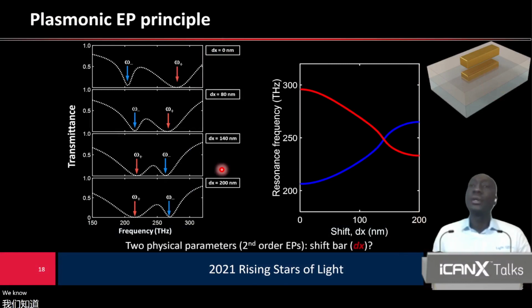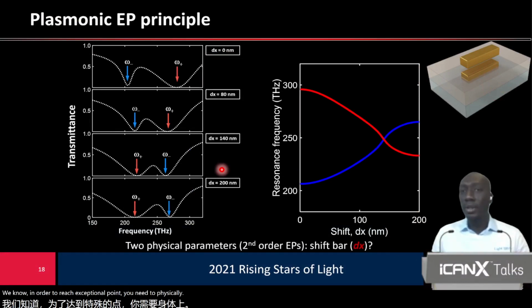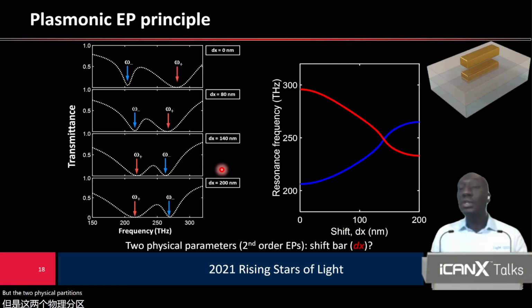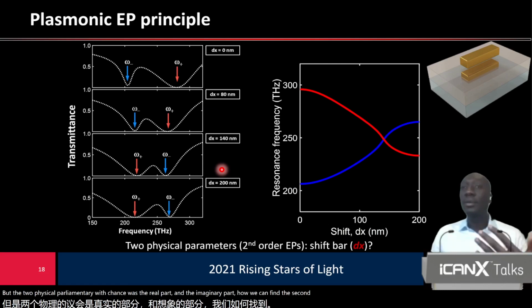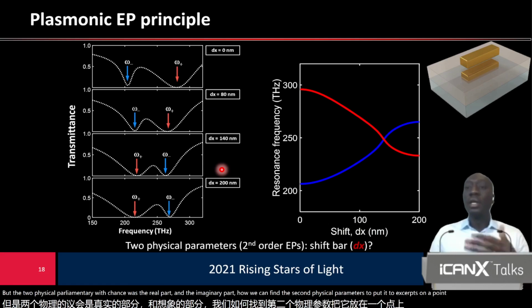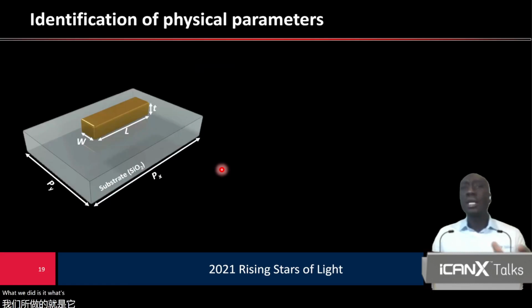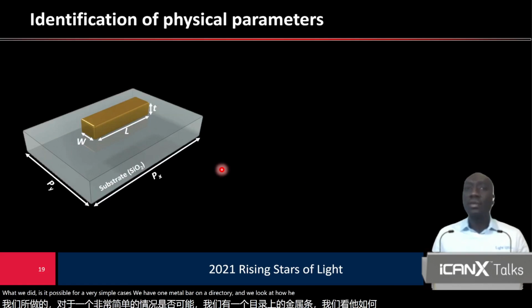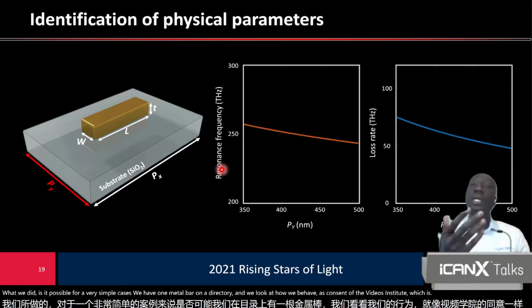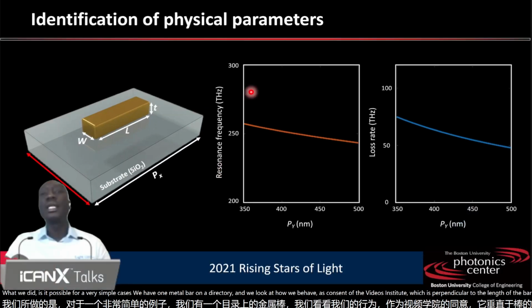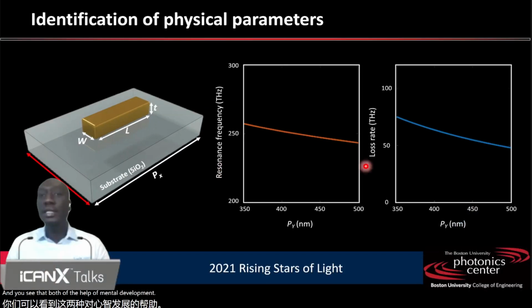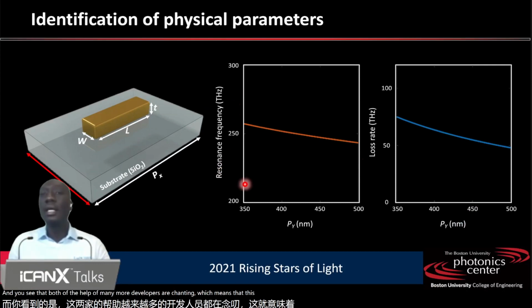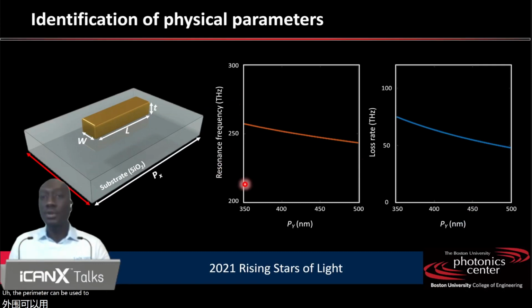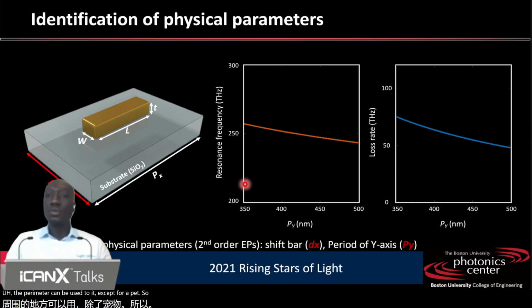We know that in order to reach an exceptional point, you need two physical parameters. But the two physical parameters should change both the real part and the imaginary part. How can we find the second physical parameter to reach the exceptional point? What we did is consider a very simple case. We have one metal bar on a dielectric, and we look at how it behaves as a function of the periodicity, which is perpendicular to the length of the bar. You see that both real part and imaginary part are changing, which means that this parameter can be used to reach an exceptional point. So this will be the second parameter.